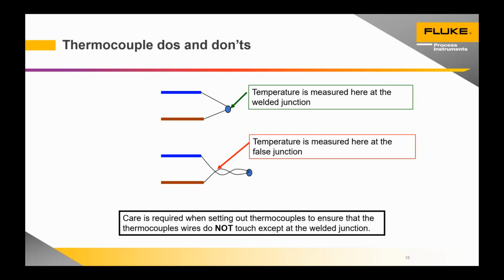Now, in a very well twisted together wire, not an issue. If it's loosely twisted, as the thermocouples heat and go through the process, it could well be that the first place they touch will actually move backwards and forwards along the twisted pair, giving you a very odd result. These false junctions will occur anywhere on a thermocouple where the insulation's been compromised and the two wires touch each other. So, misleading results you weren't expecting. The first place to look is along the length of the wire. Look for damage on the thermocouple.